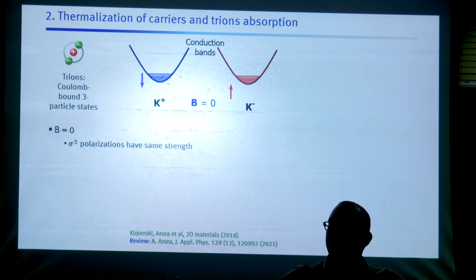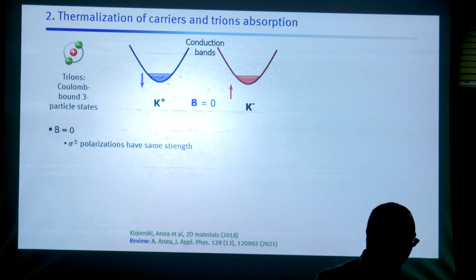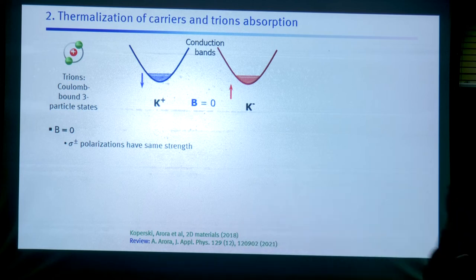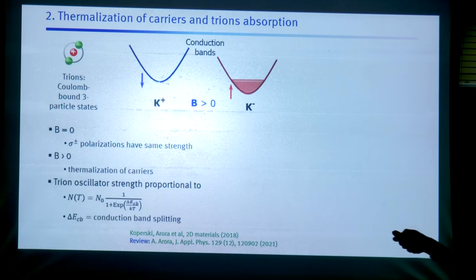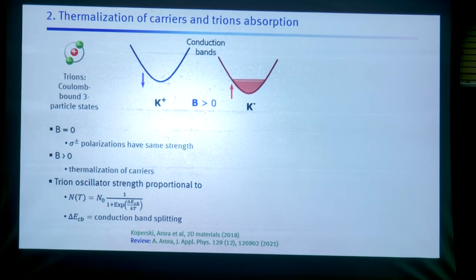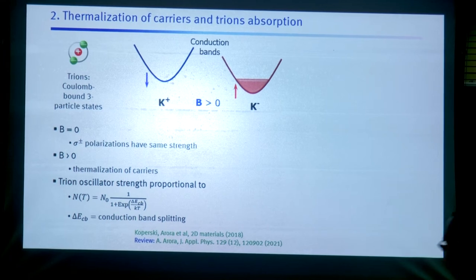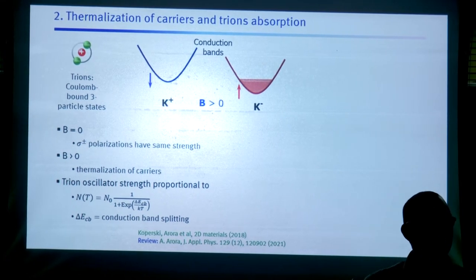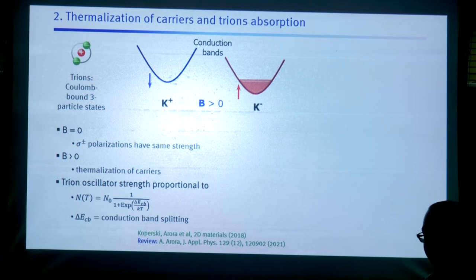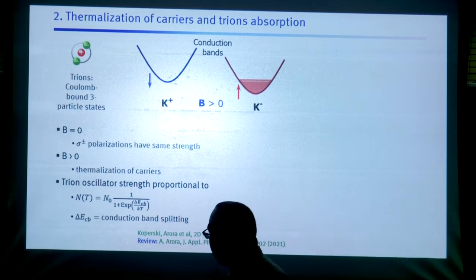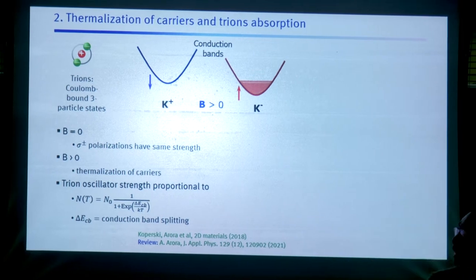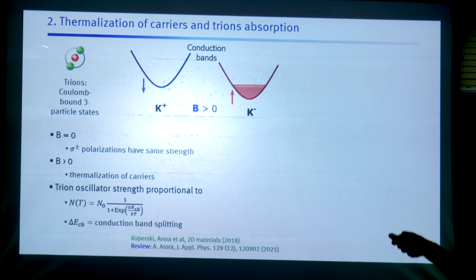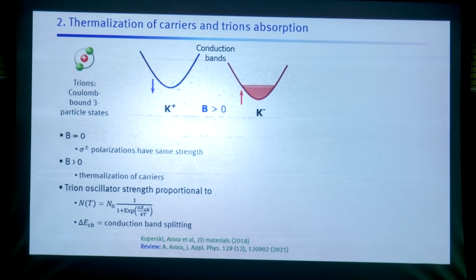But once you apply a magnetic field, if one moves up and the other one moves down, you will have a population transfer from one of the valleys to the other. So one moves down, one stays up when you apply a magnetic field, and you have population transfer. That means we should be able to directly study the Zeeman effect of the conduction band, because earlier we were able to probe only the Zeeman effect of excitons. But if we do this, we should be able to directly study the Zeeman effect of the conduction bands.